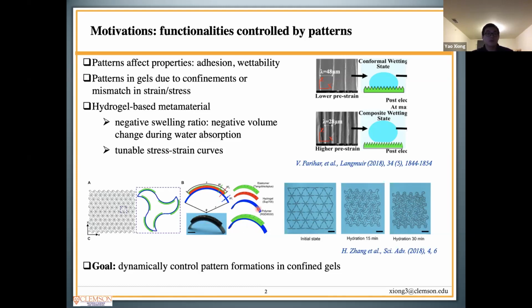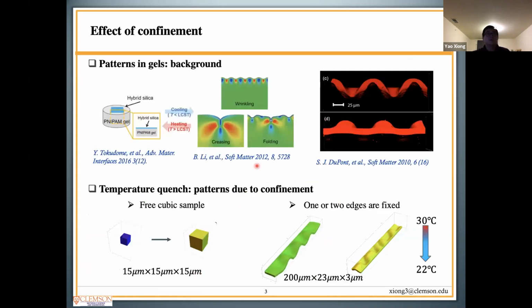This material is composed of polymer hydrogel and elastomer. Due to the swelling of the hydrogel, these initially straight beams are bent, leading to the reduction of the structure size. It also shows a tunable stress-strain curve by controlling the time of hydration. Our research goal is to dynamically control the pattern formation in confined hydrogels. Here I show some examples of swelling-induced patterns where hydrogels are confined by attaching the surface to a skin or